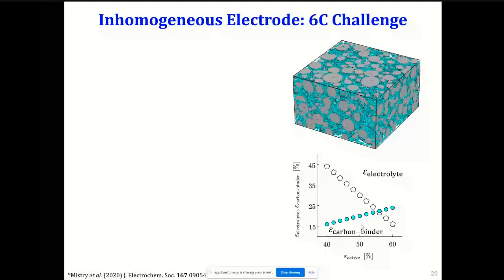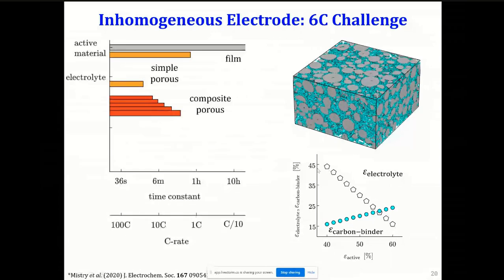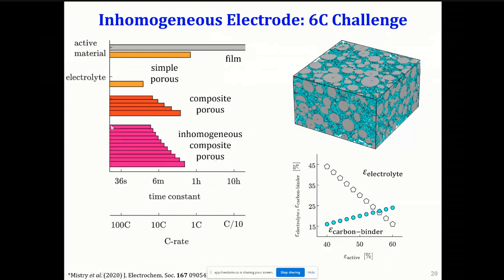So just to point out, look at this data point. You have a 60% active material, but your corresponding porosity is about 15%, which is really, really terrible, right? And you can now do these calculations locally and then go back to this time constant plot. And what you would end up with is that within the same electrode, you would have this distribution of time scales. So you would have a distribution of transport time scales.